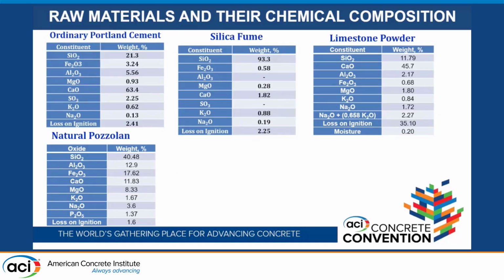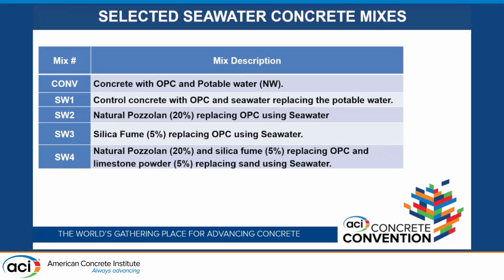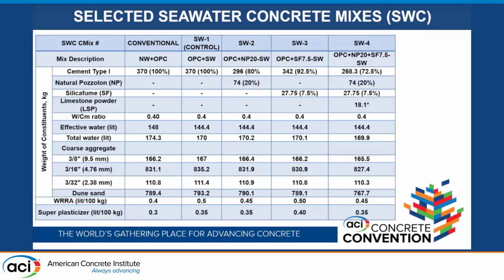These are the raw materials which are used: OPC, silica fume, their chemical composition, limestone powder, and also natural pozzolan, which is available in the western region of Saudi Arabia, and a large quantity was also used in this particular work. After a lot of trials, more than 50 to 60 mixes, we finally converged to these 5 mixes of different types, which were concrete with OPC and potable water, NW, and then concrete with OPC and seawater, replacing the potable water. Then we tried other supplementary cementitious materials like natural pozzolan, 20%, replacing the cement, and using seawater, and then silica fume, 5%, replacing the OPC. Actually, it was later increased to 7.5% using seawater, and natural pozzolan plus silica fume plus limestone powder. These are the 5 concretes which we finally decided to carry out detailed investigation on.